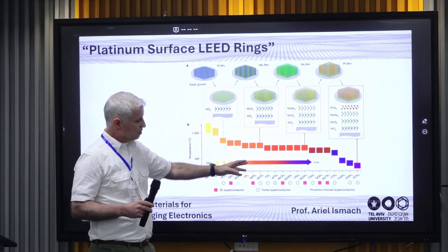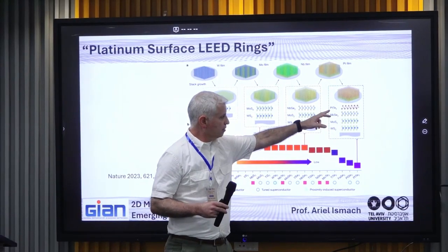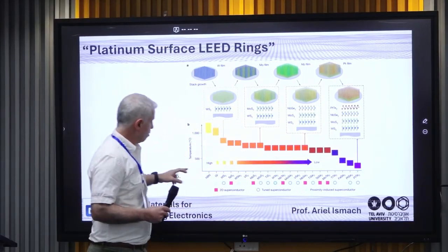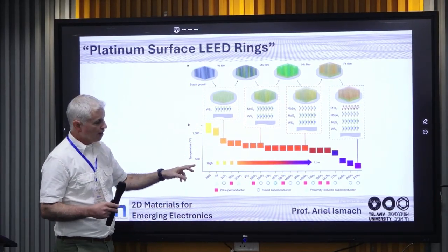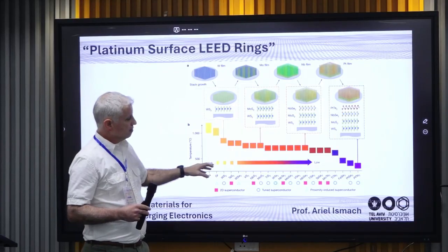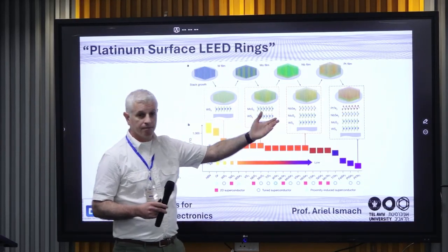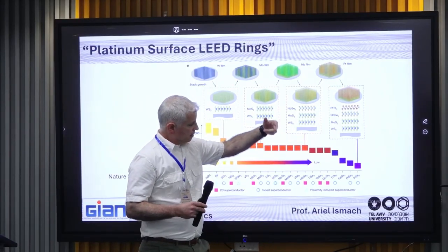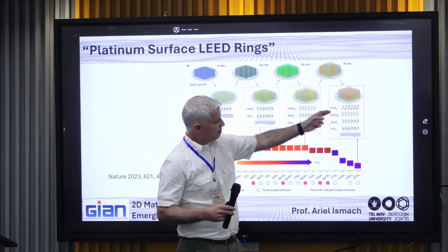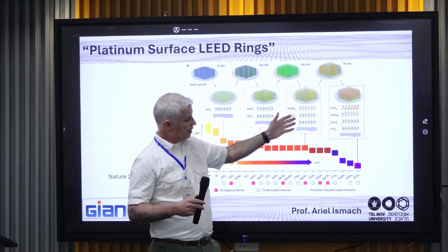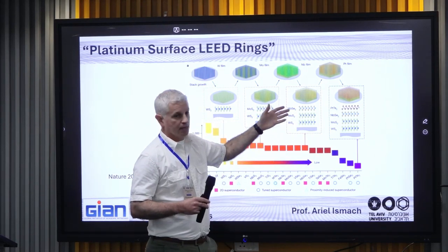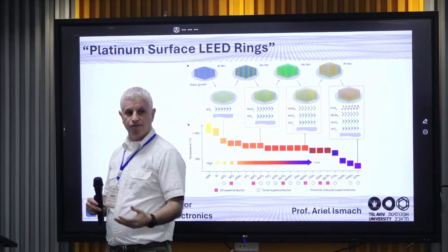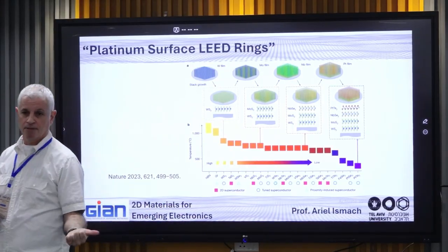According to this work, for example, the platinum telluride requires the lowest temperature, below 500. So that's why they do it at the end. Okay? Because in order to synthesize the platinum telluride, they need to heat at less than 500, so they reduce the chances of damaging the previous layers.